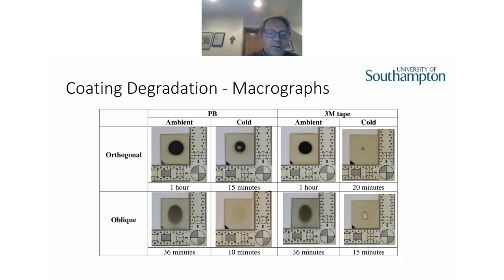These are the samples that we pictured after the test. The top row is at 90 and the bottom row at 45, ambient and cold, for the polyurethane brushed system against the 3M tape. There is some discoloration, they're all blackened in some way, and we haven't quite bottomed that out, but that is possibly a clue. You can see the scars and depth varies depending on temperature.